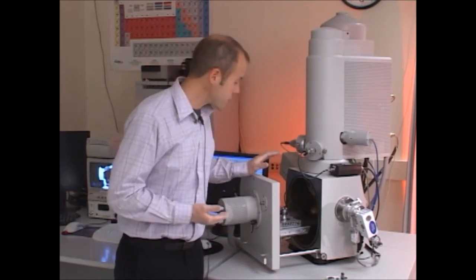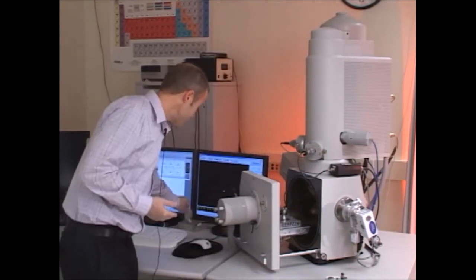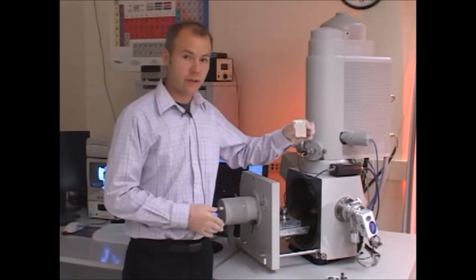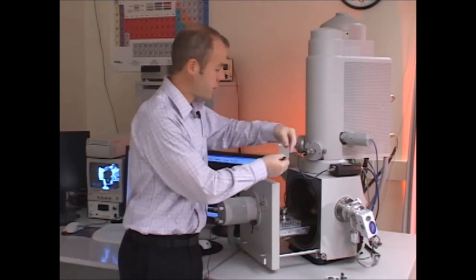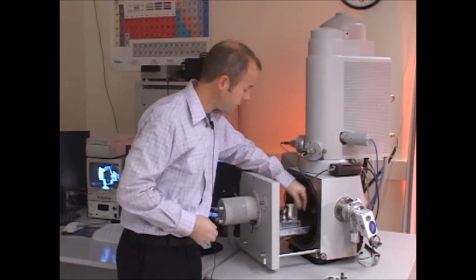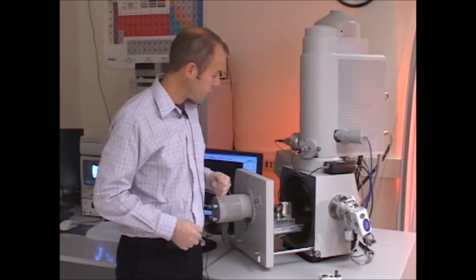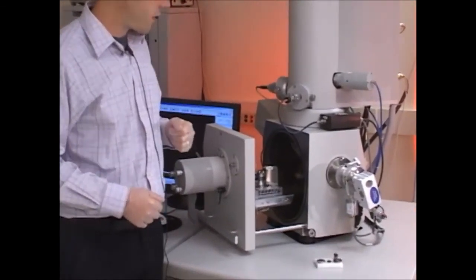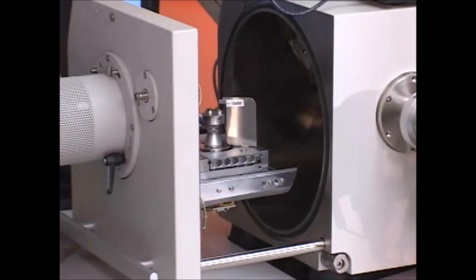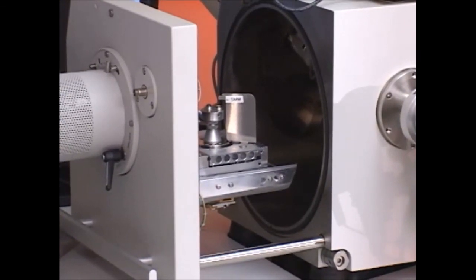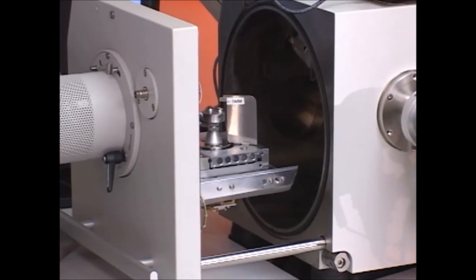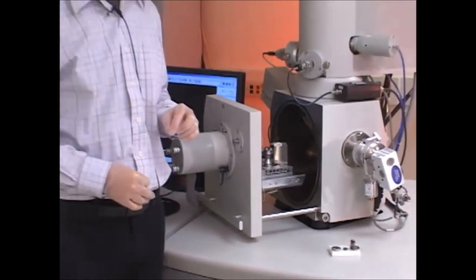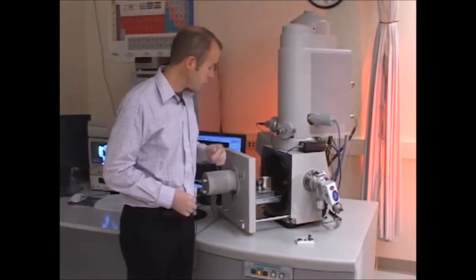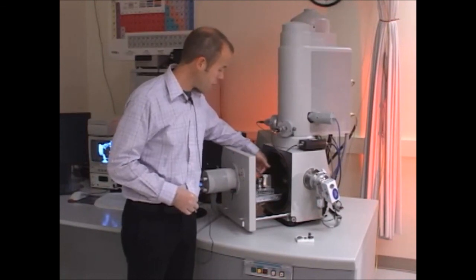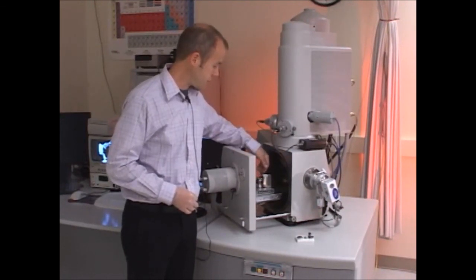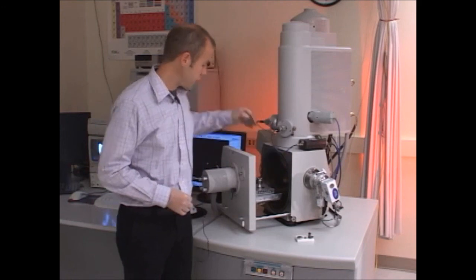So I'm going to measure the height of this sample with what we call the elephant ear, just by placing this small gauge on the stage alongside the sample. And you see there's 5 millimeters marked. That represents 5 millimeters of clearance from the detector. So anything that's closer than 5 millimeters to the detector is too tall to be accommodated in this chamber, and it would have to be remounted before we could look at it. But as you can see, all of these samples are well below 5 millimeters in height, so it's safe for me to close the chamber door. So I'll just remove the elephant ear.